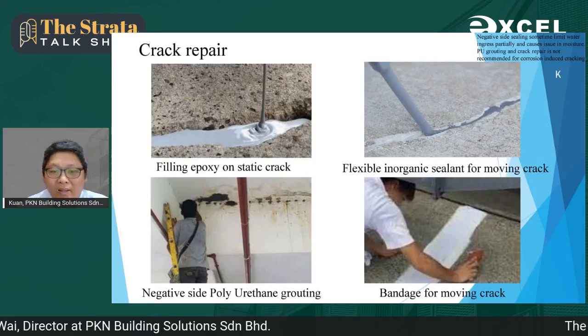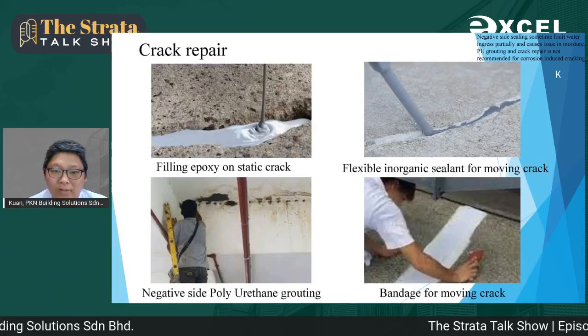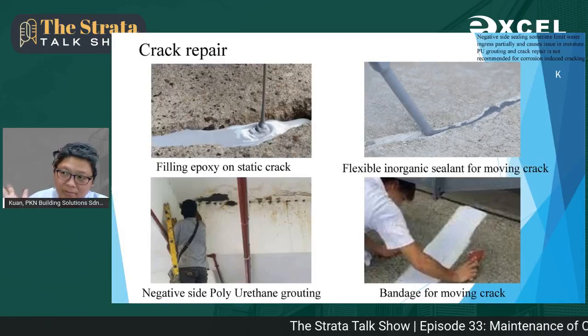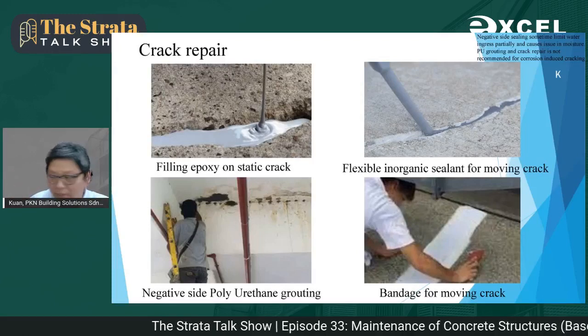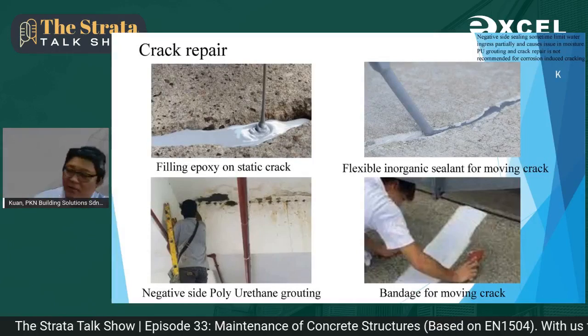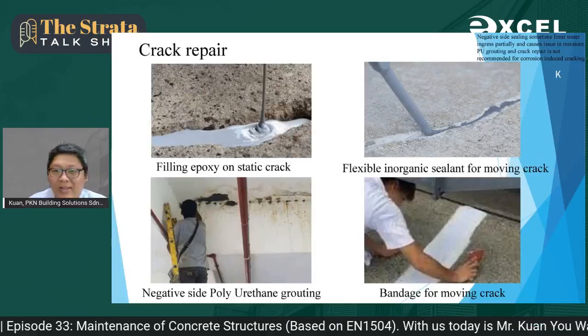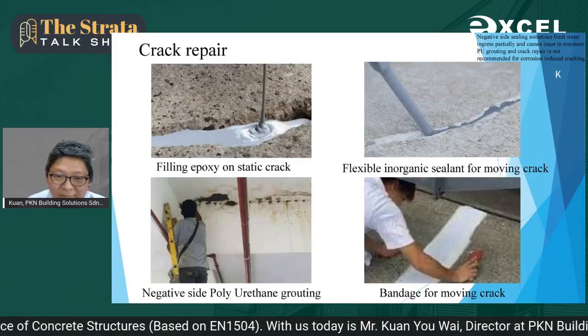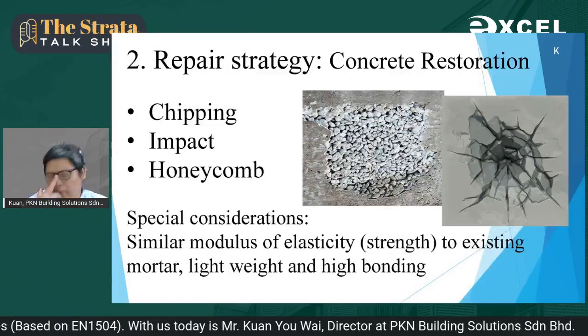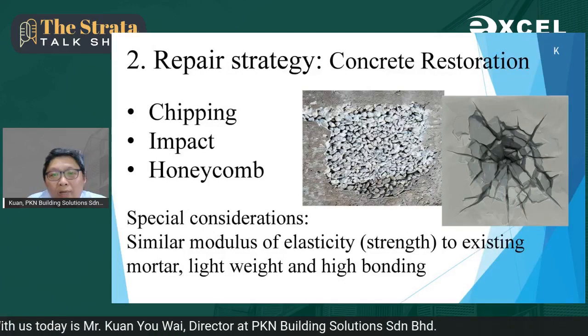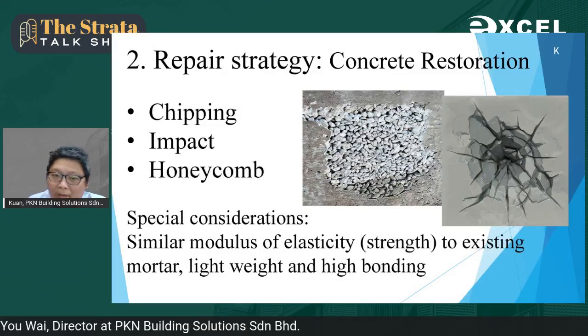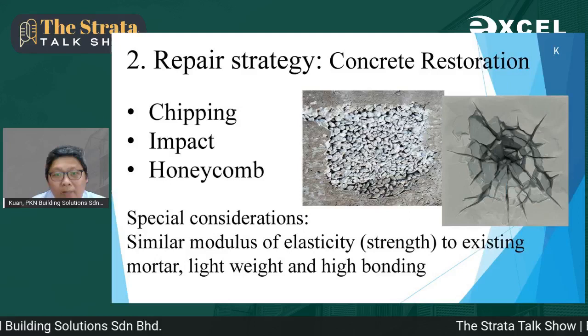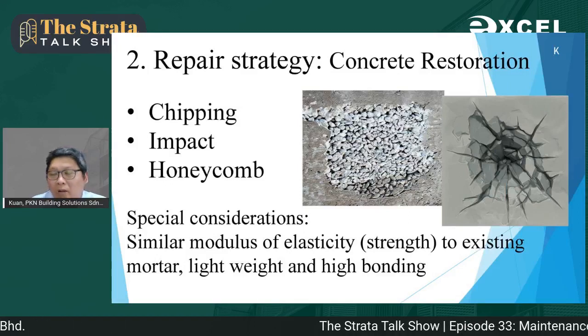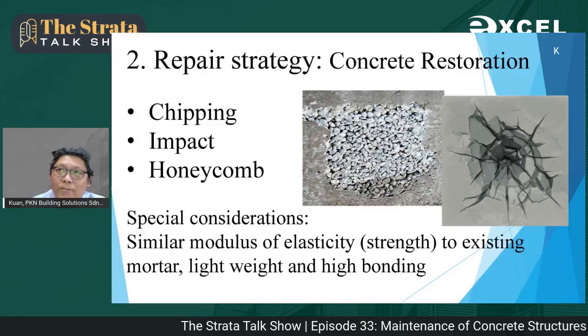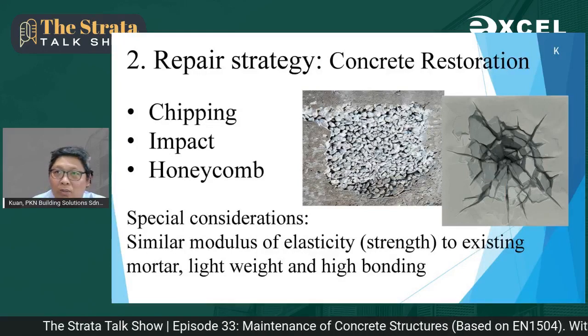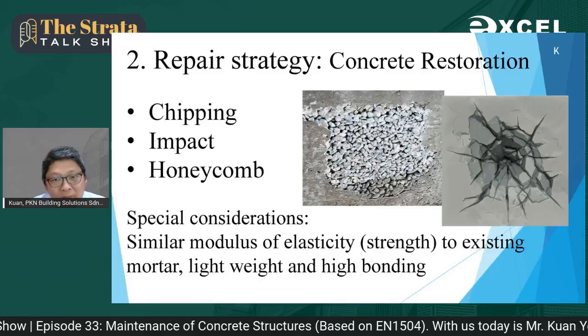Okay, and bandaging is actually a very useful way. We actually use elastic type of membrane, like for instance the single ply membrane like this, to bandage the crack, just like the bandage that we put on our wound. Okay, so of course, when it comes to non-structural repair, say due to honeycomb or due to impact, we can patch back. The patching back is very important because it restores the strength, I mean it improves the resistivity to the infusion of water as well as the carbon dioxide.